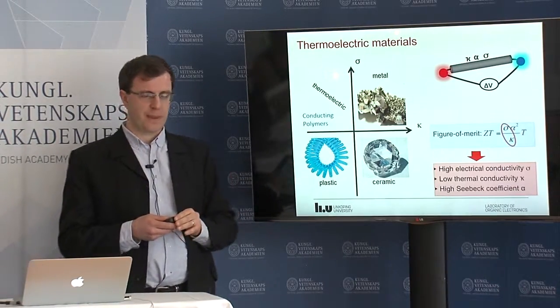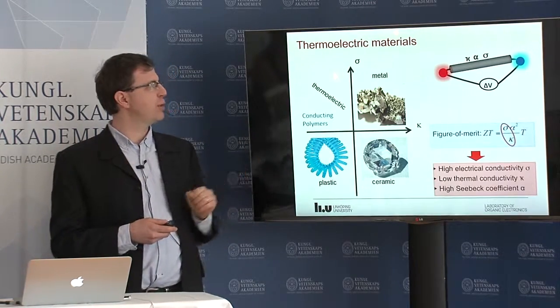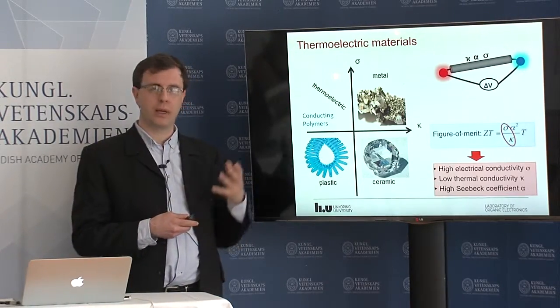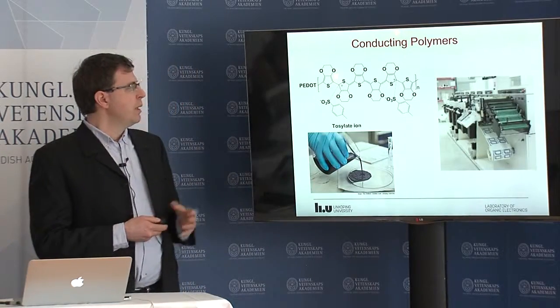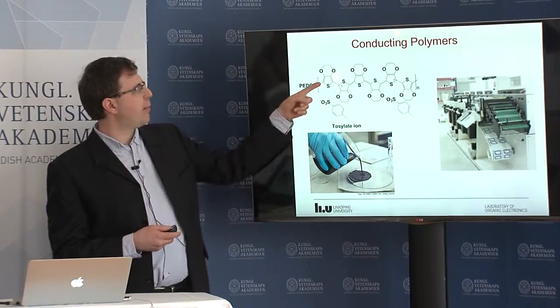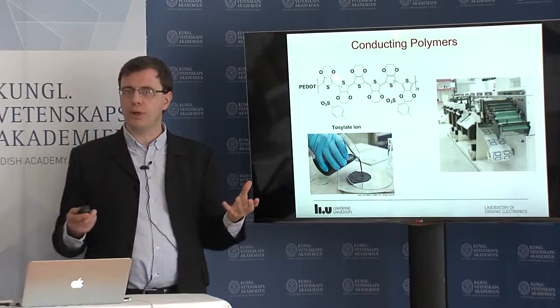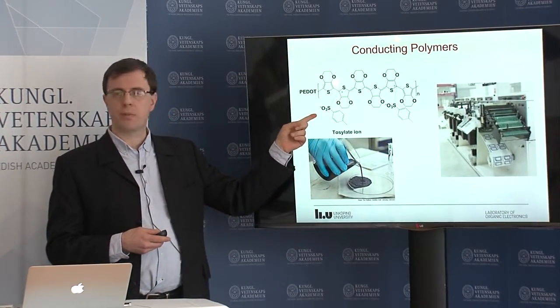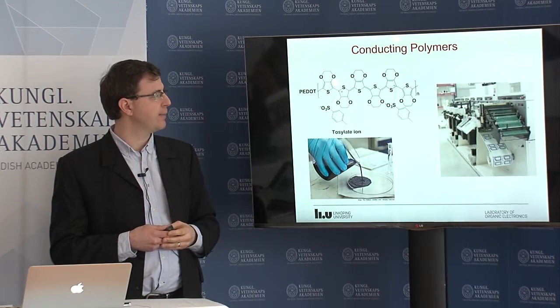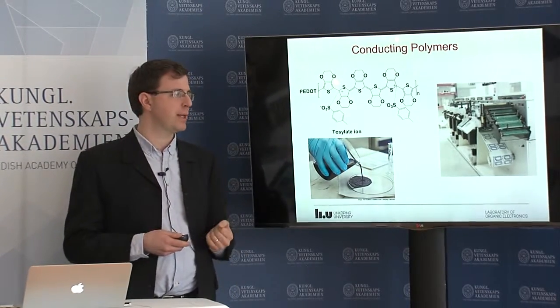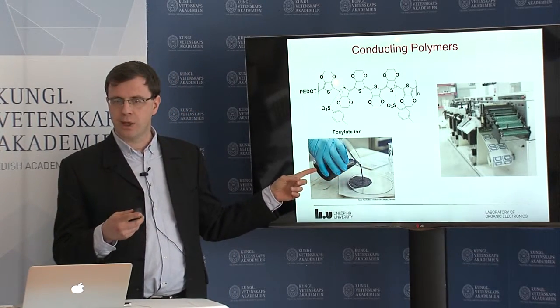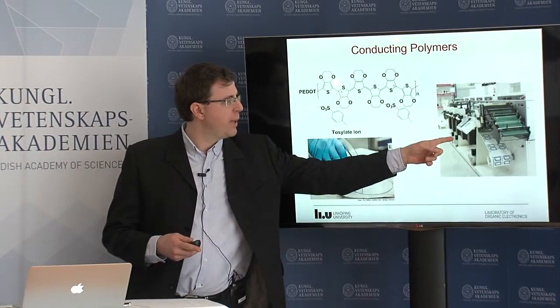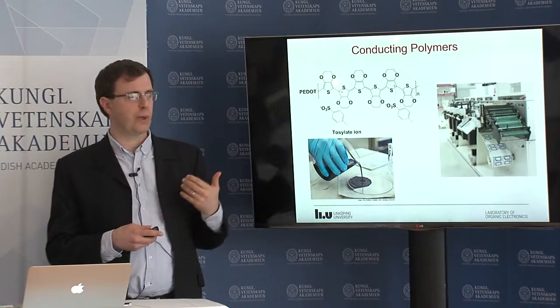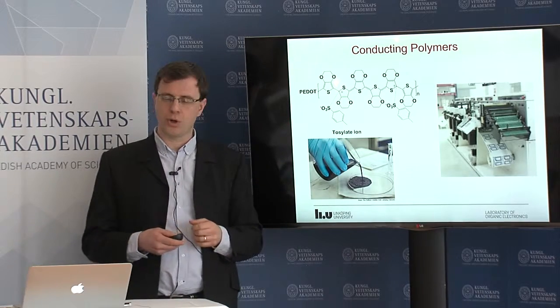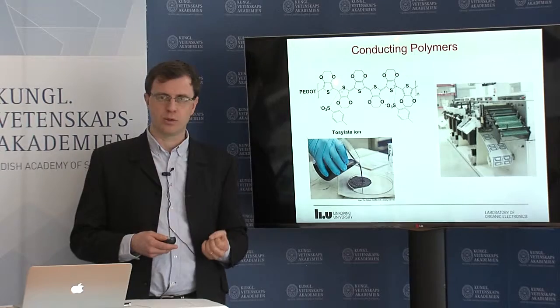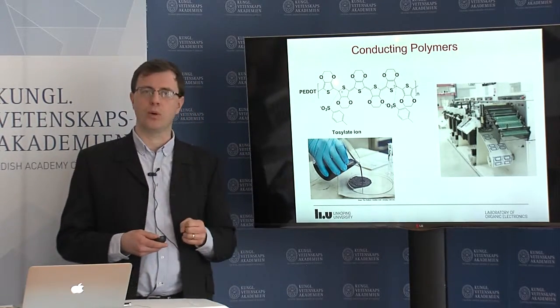So since I've worked on conducting polymers for years, when I saw that opportunity, I thought let's try to investigate if it's possible to make a thermoelectric material with conducting polymers. And this is an example of a conducting polymer. You see it's based on carbon atoms that we don't see here, sulfur and oxygen atoms. So they are all very abundant on Earth. So if we can make a thermoelectric material with that, it would be a quite interesting finding. Moreover, one of the interesting things with polymers is that they can be solution processed, which means that eventually you can create a thermoelectric ink, and use a big printing press to print thermoelectric generators on plastic foil or paper. And that would also be another key advantage in terms of manufacturing cost. So both the low cost of the material and the low cost of manufacturing would be a key point.